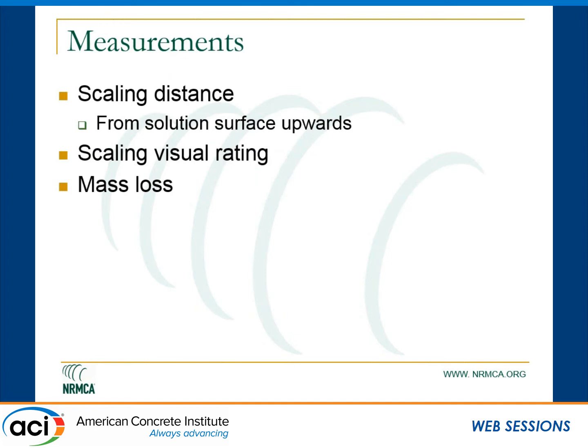We measured the scaling distance, as scaling progresses from the solution interface upwards. We also did a visual scaling rating — similar to the freeze-thaw scaling rating — and a mass loss study. The mass loss study had some problems: after immersing specimens for one to two years, we also started seeing chemical sulfate attack at the bottom. So that mass loss is partly due to chemical attack, which mixes up the failure modes and makes it very hard to get good data from that measurement.